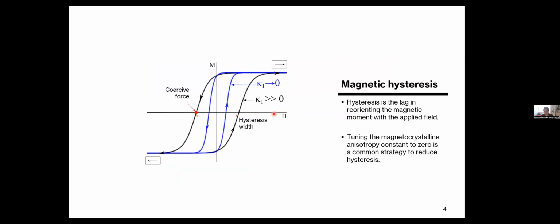So what that looks like is if we just take a simple hysteresis loop. Here we have the applied field that's denoted by H, and the average magnetization in your material that's denoted by M. And here you see some schematics of the magnetization in your body. You apply an external field, you switch the magnetization, and it traces out this characteristic hysteresis loop. The external field at which the average magnetization in the system is 0, we call that coercive force or coercivity. And the width of the loop is what I will be referring to in this talk as the hysteresis width.